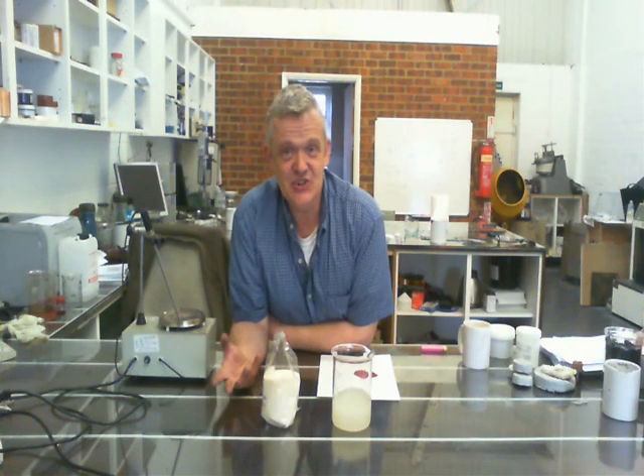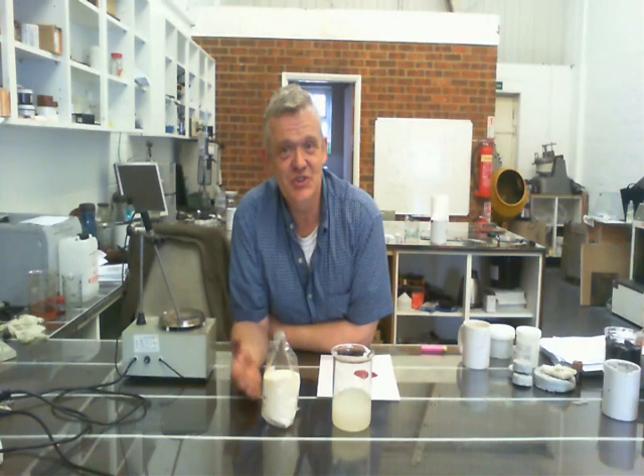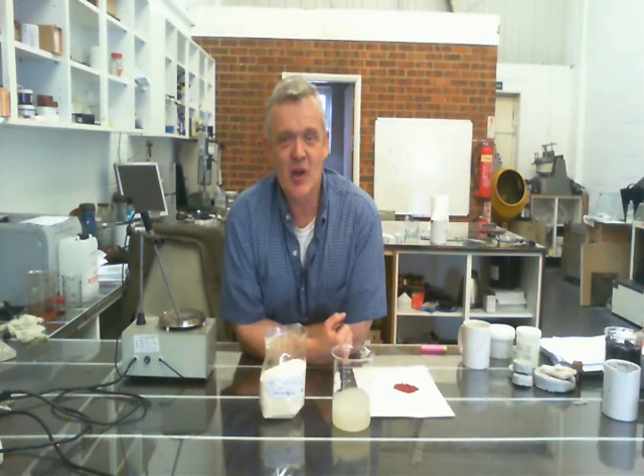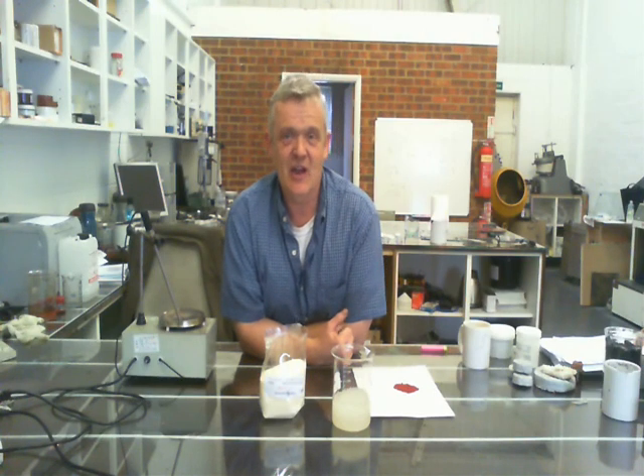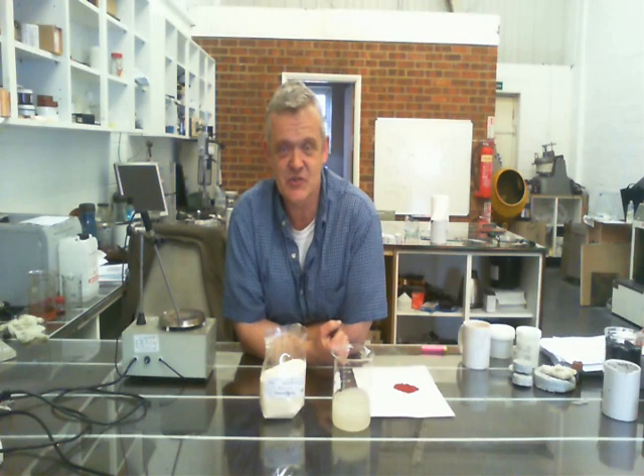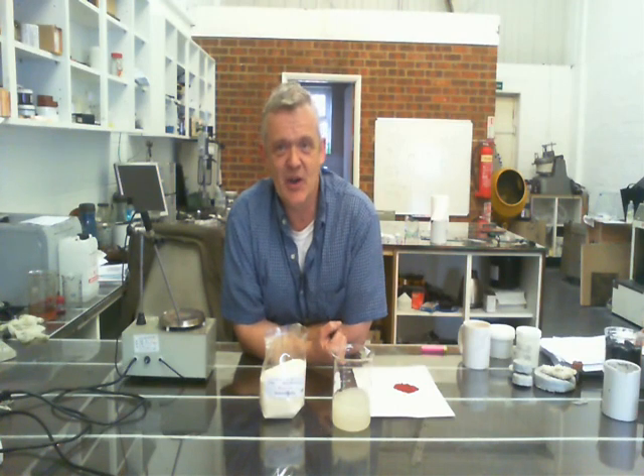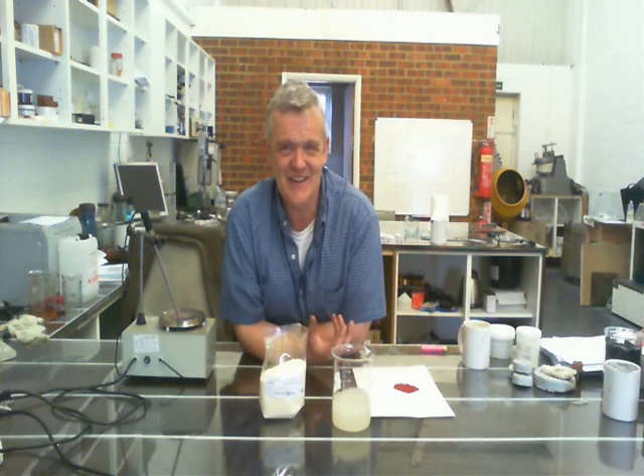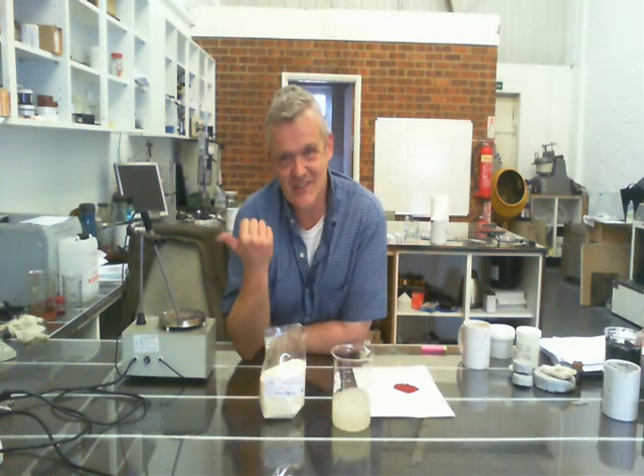So one of the things is a weak solution. Another one is an appropriate capping agent. Another one is an appropriate synthesis condition. Which synthesis condition? Choose. There's lots of ways of manipulating that sort of stuff. Now, I have quite an interest in copper nanoparticles because I have a particular interest in photosintering nanoparticles into conductive tracks. And one of the problems with copper nanoparticles, or any nanoparticle actually, is to get them to disperse. It's quite challenging.